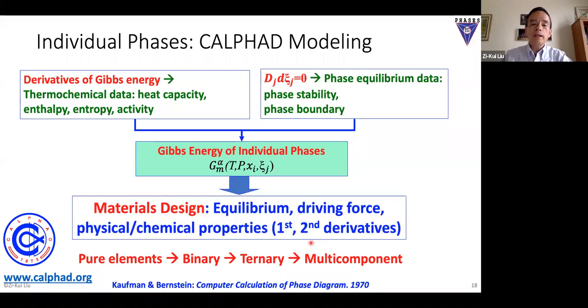So as soon as I get a database, you can do the material design. You can do equilibrium calculation. You can talk about the lifetime - for example, how long it takes for that detrimental phase to form. You have driving force. You can calculate the properties from first and second derivatives of the energy function.